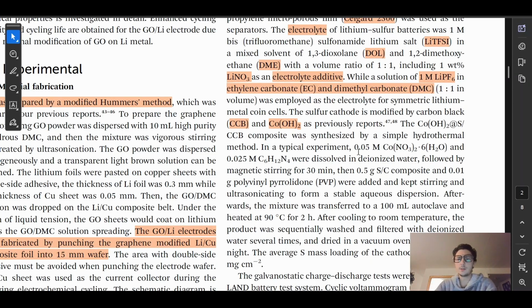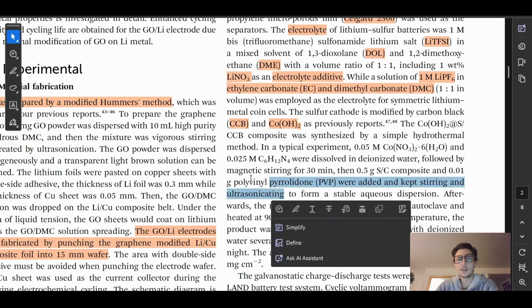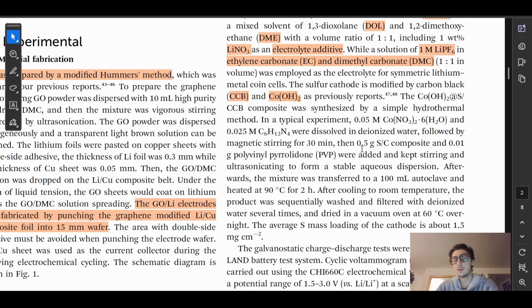In a typical experiment, 0.05 molar, I think this is cobalt nitrate hydrate, and 0.025 molar C6H12N4 were dissolved in deionized water, followed by magnetic stirring for 30 minutes. Then 0.5 grams S/C composite and 0.01 grams polyvinylpyrrolidone, PVP, were added and kept stirring and ultrasonicating to form a stable aqueous dispersion.